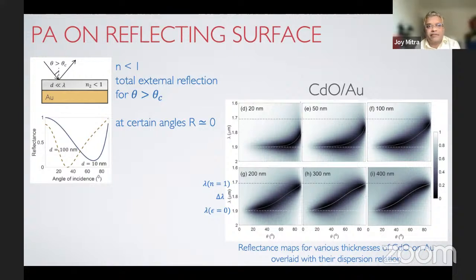These are not bulk films. All these films are of the order of 100 nanometers and below. While I haven't done a depth profiling, we have done it on various thin films like 20 nanometer, 50 nanometer, 70, 100, 120. What we saw was that the number density calculations from the optical measurements, and also our Hall measurements, follow each other and are extremely robust.